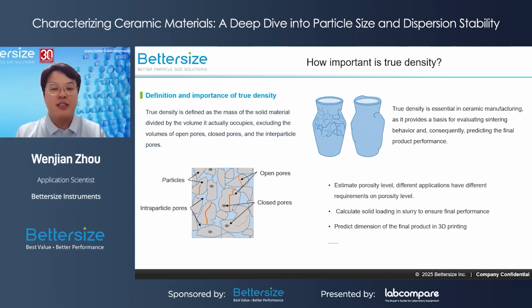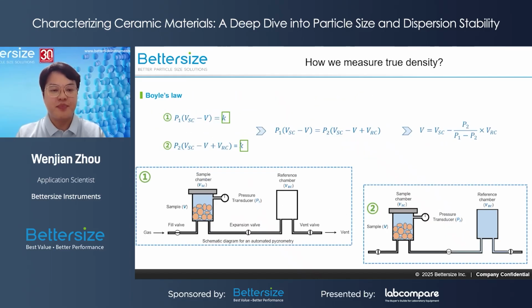And the true density allows us to optimize slurry solid loading. When preparing a slurry for casting or 3D printing, knowing the true density ensures the right particle volume fraction, which can prevent structural defects. True density also helps us predict the shrinkage and the final dimension. Using true density, we can calculate how much shrinkage to expect and optimize design so the final part is the correct size. In short, understanding it lets us achieve precise and high performance ceramics every time.